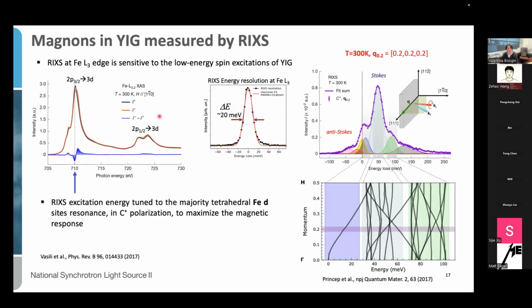As I mentioned before, the first step for doing RIXS is to measure the X-ray absorption of the material and then select a resonant energy to perform our resonant inelastic X-ray scattering measurements. So this is the X-ray absorption of Yttrium Iron Garnet at the iron L edge, which corresponds to the 2p to 3d transition. And this we measure with circular polarized, positive and negative polarizations.